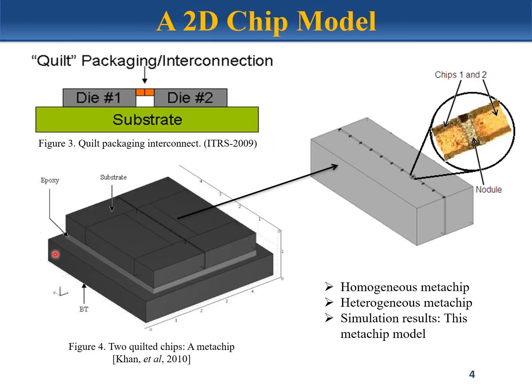Here we can see the structure that was designed and created for the simulation. It resembles the quilt packaging method discussed in the previous slide. As discussed before, we can see two silicon substrates sitting on a carrier where the nodules are connecting the copper traces of the two different substrates. On the right side here, we can see a zoomed in version of the nodules and even more zoomed in version or a microscopic image of the nodule itself. Here we can see the chips on both sides with the nodules in the middle.